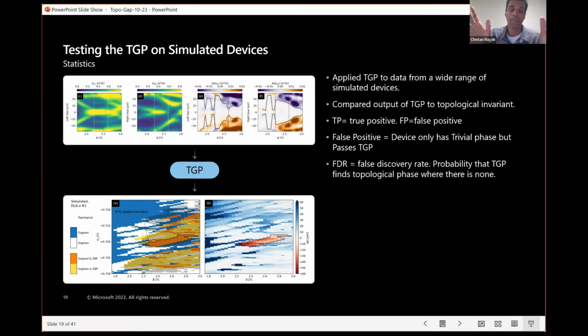There are two things to point out. First of all, technically, this whole region here is topological. See, it's all hatched. So this yellow region, there's a very small yellow region here that's not hatched. Most of this yellow region is hatched. So it is topological, but the gap is very small. The gap is smaller than our threshold, because here we're setting a threshold of about 10 microvolts, and it is topological, but just a very small gap.